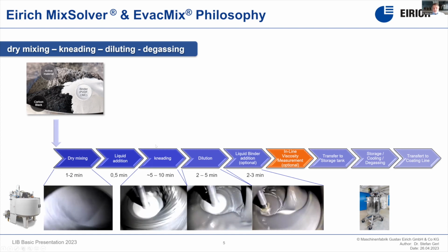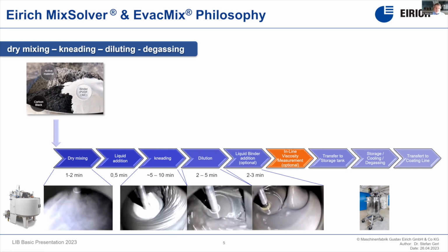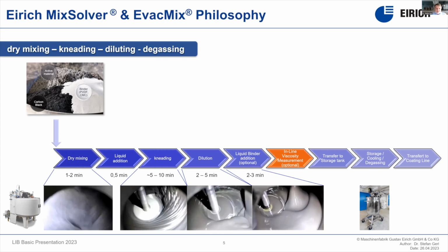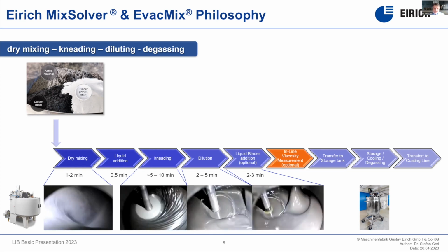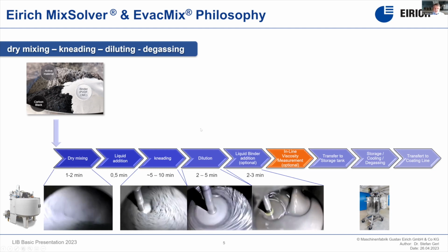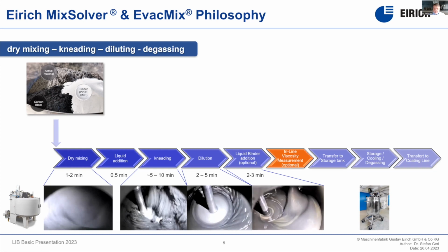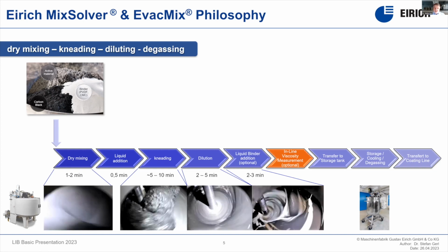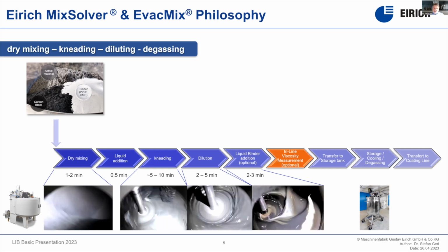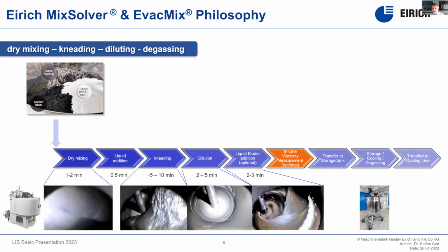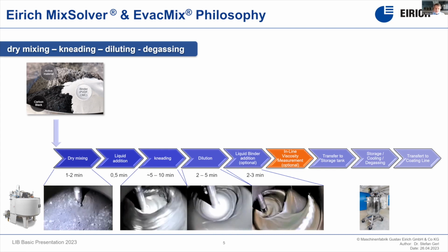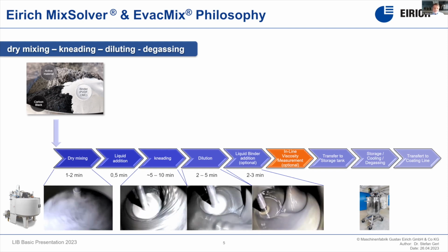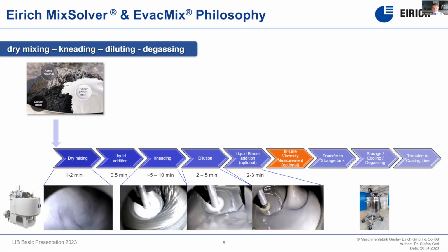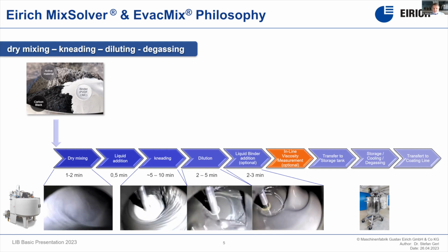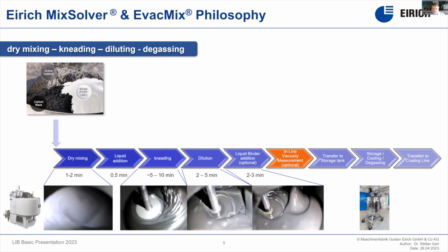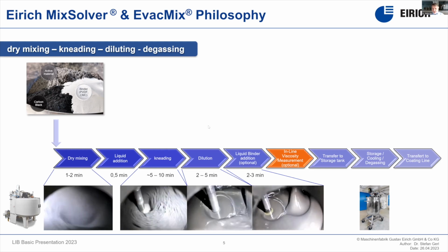After this, we are adding a first portion of liquid, typically around 50%, to reach a full plastic body, which is always named in Asia as a hard kneading. Within this hard kneading phase, we are first of all dissolving the binder, and we intensively shear the system to disagglomerate, to wet, to disperse the carbon black to form a good electrode network. You need a certain minimum shear rate, but we see that after roughly 7 minutes, we already achieve such a good quality that we have a properly dispersed active material, a properly dispersed carbon network, and we can reach a good coating slurry.